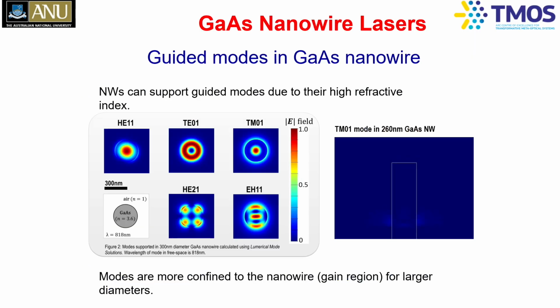And so again, simulations really play an important role in determining what the diameter of the nanowires should be, what the length of the nanowires should be, and the range of things. And this is the work of my student, who is now at Imperial College, Dr. Drew Saxena, where he has shown how the light propagates in these gallium arsenide nanowires. And then you can look at the various optical modes, which you get at various field intensities. And in this one, we are showing the TM01 mode, which is propagating in a 260 nanometer gallium arsenide nanowire.